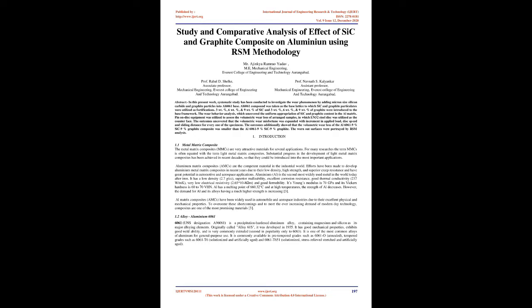Pin-on-disc equipment was utilized to assess the volumetric wear loss of prepared samples, in which EN32 steel disc was utilized as the counterface. The outcomes revealed that the volumetric wear loss increased with increase in applied load, disc speed, and sliding distance for every one of the specimens.